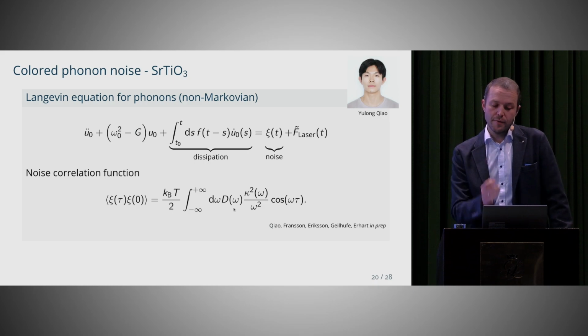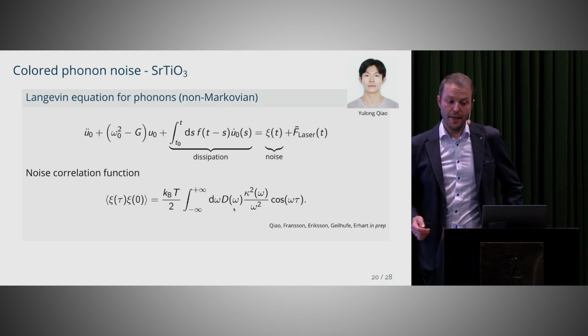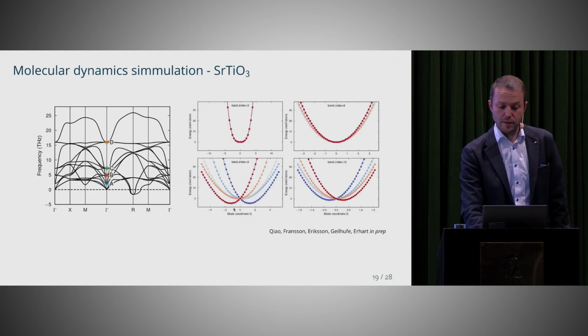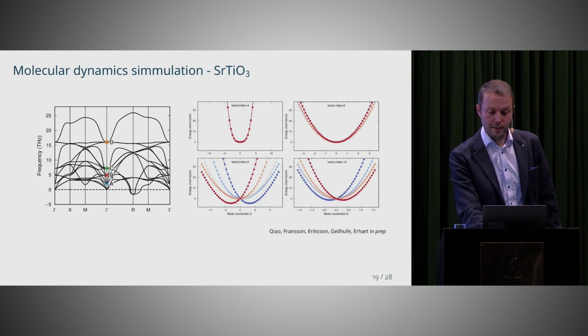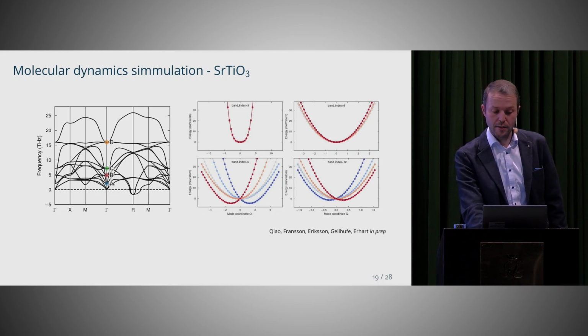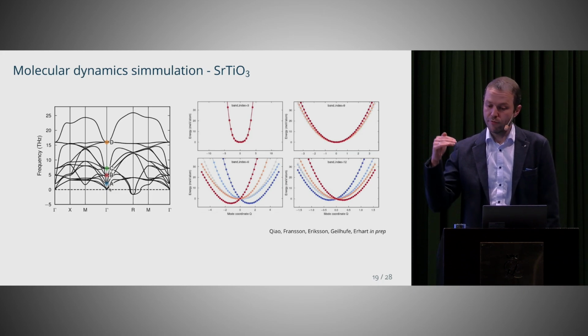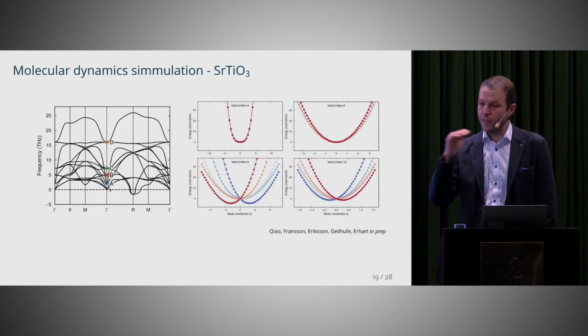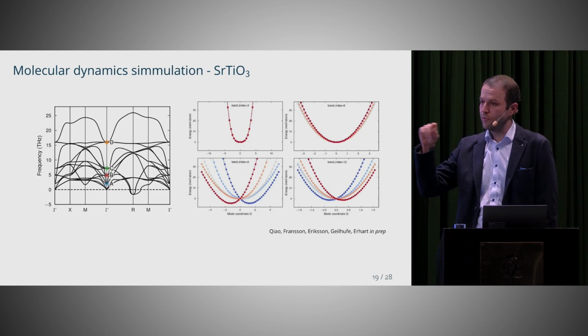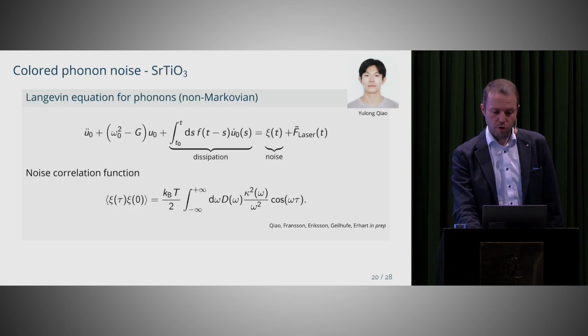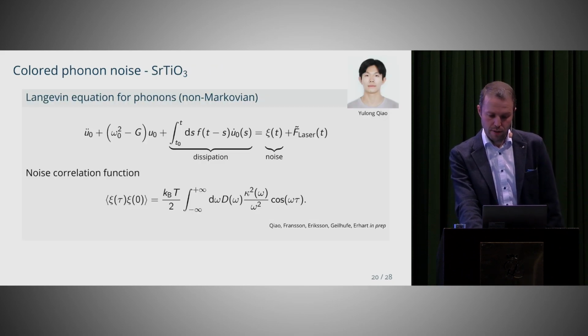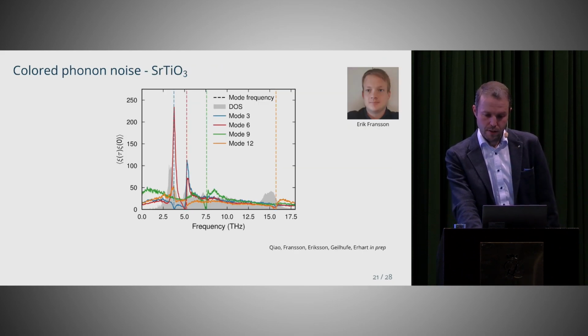And this D is a property which we call density of states. And it basically connects to this phonon band structure that one can calculate with a computer. It pretty much asks, if I take a specific frequency, how many excitations can I find at this frequency? How many different phonon modes are there? And Yulong could show that this noise-noise correlation is dependent on that one.